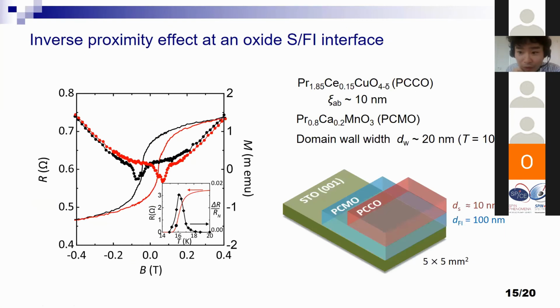And we observed something similar for oxide superconductor as well. So we had to prepare electron-doped cuprate superconductor to observe this kind of inverse proximity effect. That is because we needed to prepare a material with long in-plane coherence length. So this is 10 times longer than the hole-doped type cuprate. And this is close to the typical domain wall width of ferromagnetic insulating manganite.